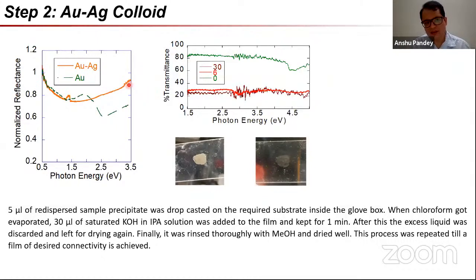Following the multiple castings of the film, what you find is that at the film stage, the films completely lack normal structural features associated with gold and silver, but rather AuAg films seem to have no detectable spectral features which are either present in gold or in silver. We have suppression of plasmon resonances. The films which you make as a result of it are white. They are again powdery solids.